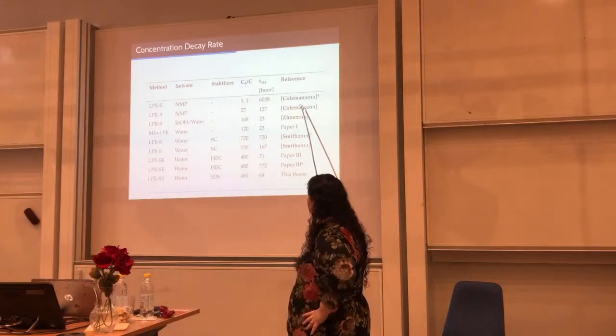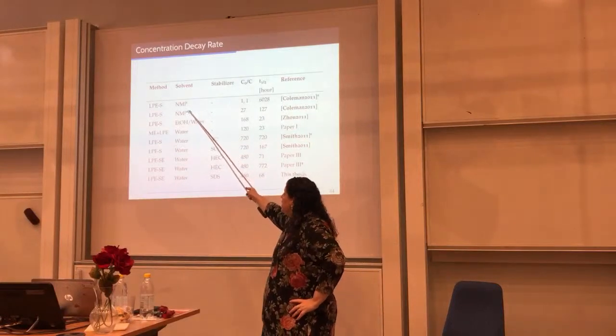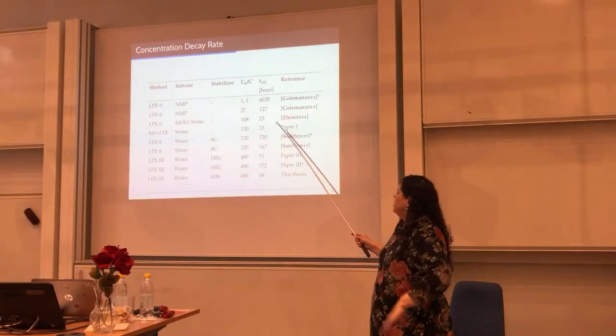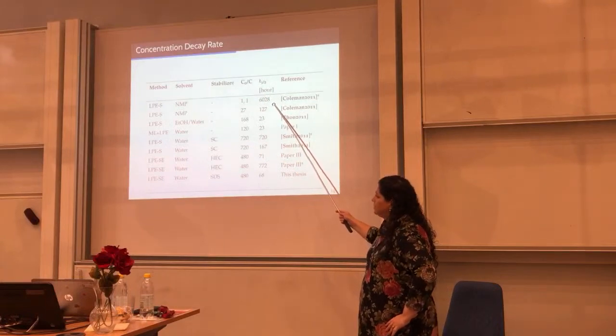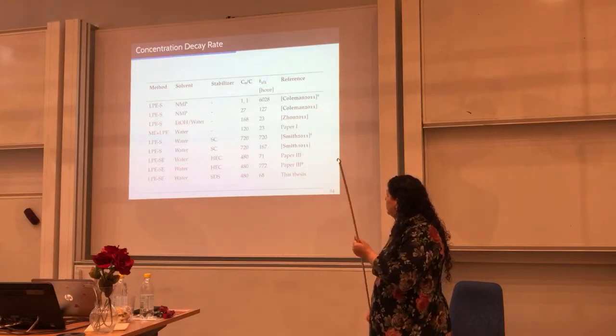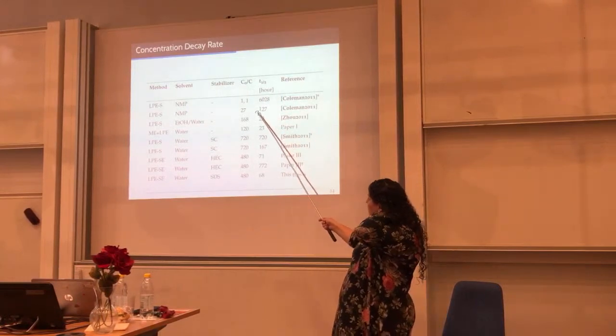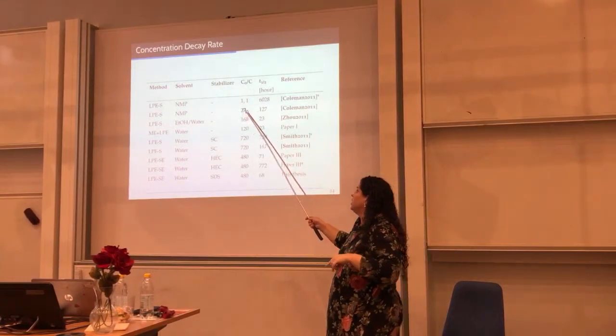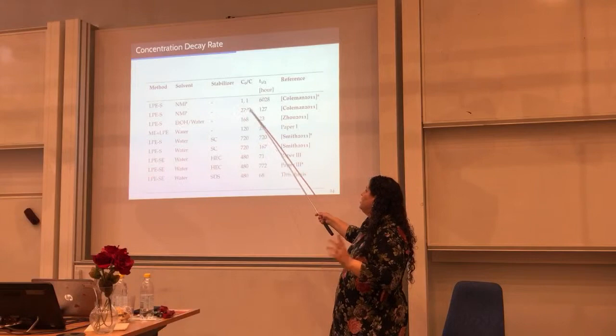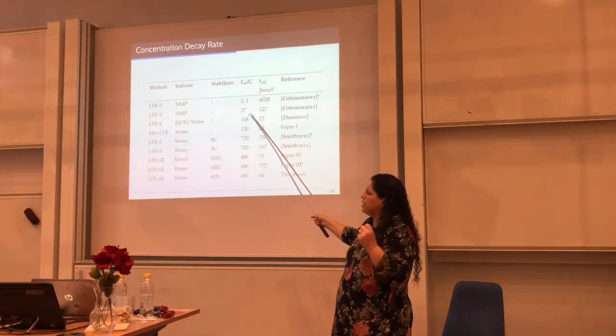So, when we take Coleman's work, they use NMP and sonication, and it's the best solvent to disperse, there is no doubt about it. So these dispersions will be stable forever, like 6,000 hours. It's a long, long, long stability. But then if we take the initial concentration, not the concentration after centrifugation, which is much lower, then this number drops a little bit, because you start with a very high concentration but also end up with a very low concentration dispersion.